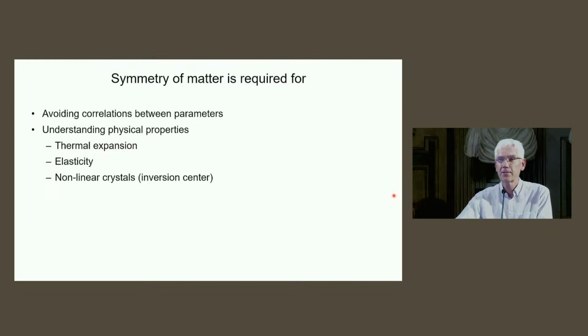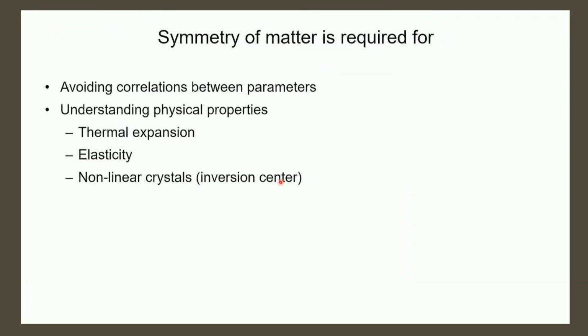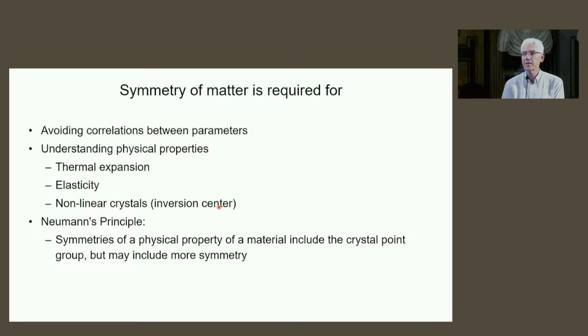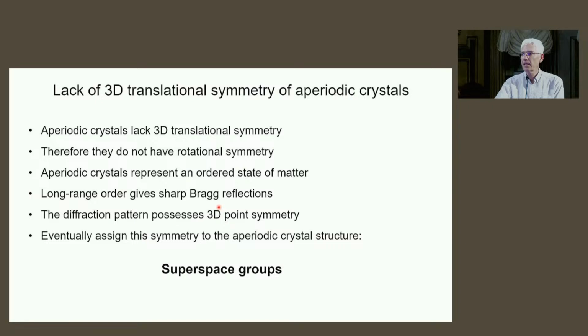And that is specifically and particularly so in crystal structure analysis against X-ray diffraction. If you forget about the symmetry, you cannot solve your structure. It's also very important for certain physical properties, as I've indicated here. Inversion center as part of the symmetry or not allows us to find out beforehand whether a crystal is a candidate crystal for nonlinear optics, or with inversion it's not. And that is all summarized in Neumann's principle, which says that the symmetry of a physical property of a material includes the point symmetry of the crystal structure, but it also may be more. And one way where it's more is the Laue symmetry of X-ray diffraction patterns, where X-ray diffraction with some small difficulties adds an inversion center to the symmetry group of your crystal.